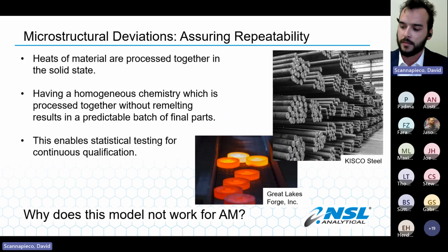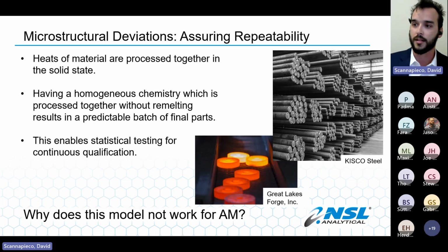When we look at getting into the microstructural deviations, I think the golden standard is always to go back to forging. You get a single heat of material, a largely homogeneous ingot of whatever material you're working with. It's forged and heat treated in groups together so that when you get to the end, the predictability between the microstructure of all those pieces is extremely accurate, extremely precise. So the testing requirements are not very severe, 1-2 components at most per batch, and that certifies tens to hundreds of parts depending on the quantity and the size.